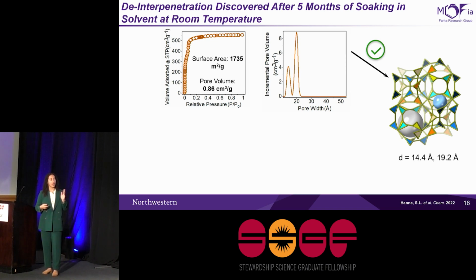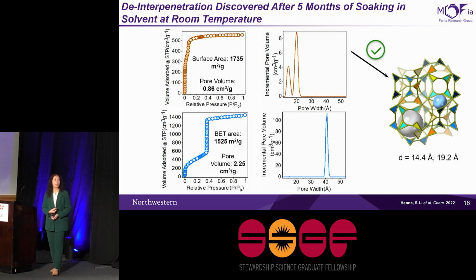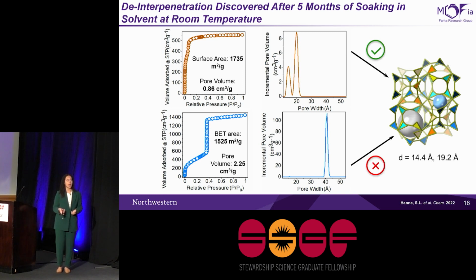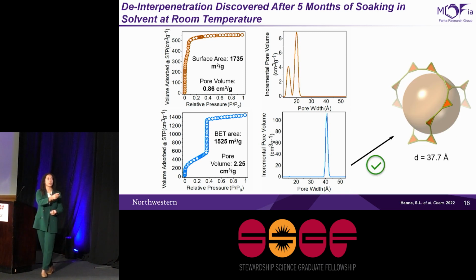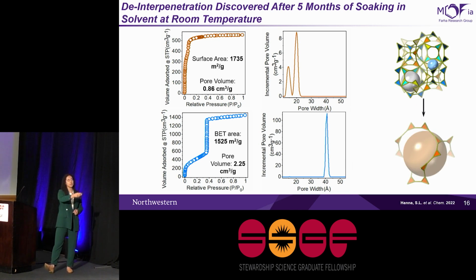But I put this project aside for about 5 months. I started working on another project, and I came back to this material, which I had left sitting in my fume hood, and I ran the exact same experiment on the exact same batch of material, and I saw a really different result. So even if you're not familiar with isotherms, you can see that the shape of this isotherm is super different, and we have a pore size now at 40 angstroms instead of 20 and 15, which clearly does not match up very well with what you would expect. This, however, does match up with what the non-interpenetrated pore size looks like, about a 40 angstrom pore. So this was the first of several clues really showing that there was this transformation from this densely interpenetrated structure to a much more open structure.